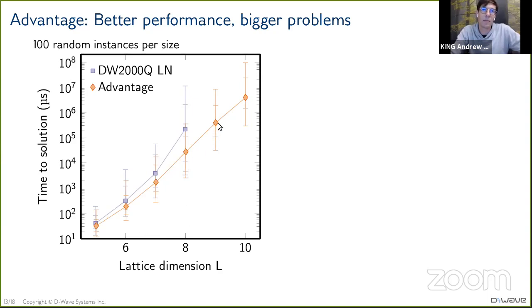What we're seeing here is the median and then 25th, 75th, 10th, and 90th percentiles of the 100 instances in these error bars. And you can see a pretty clear scaling advantage opening up over the previous processor. This is almost an order of magnitude. And then in the 90th percentile, it's about 50 times improvement in time to solution. So what I've done is I've attempted to optimize the anneal time, but we can't find an optimal anneal time for the smaller instances.